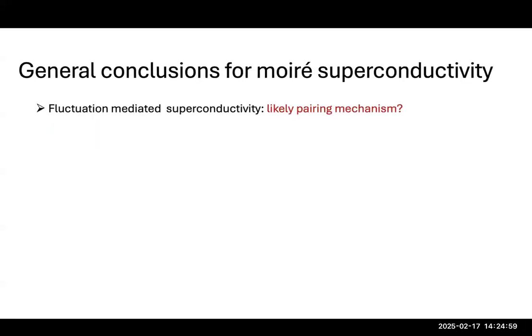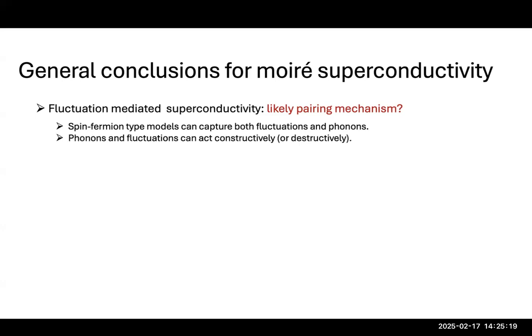So what are the general conclusions for moiré superconductivity? If you're thinking about fluctuation mediated superconductivity, I think this is maybe one of the more likely pairing mechanisms, and you can very naturally capture it with these spin fermion type models, where you just couple the electrons to fluctuations of the boson. And what we've seen from this is that, especially for the case of TBG, when people talk about is it phonon mediated or fluctuation mediated or electronic correlations, these things can act constructively and they can both contribute to a certain pairing channel, and it doesn't have to be that this is the mechanism or not. It can be more of a constructive versus destructive interference way of thinking of things.